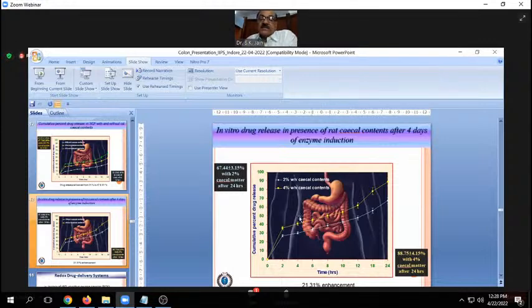Then we sacrifice the animal, isolate the cecal content, and mix it with the simulated colonic fluid, right, and perform the in vitro release study. Then we find that on increasing the concentration of the cecal content from 2 to 4, the drug release increases to 21%. So that is due to the increasing polysaccharide enzyme.